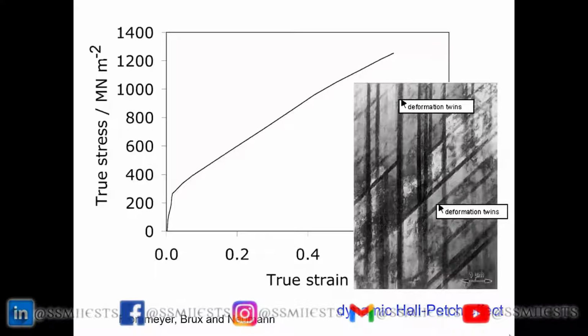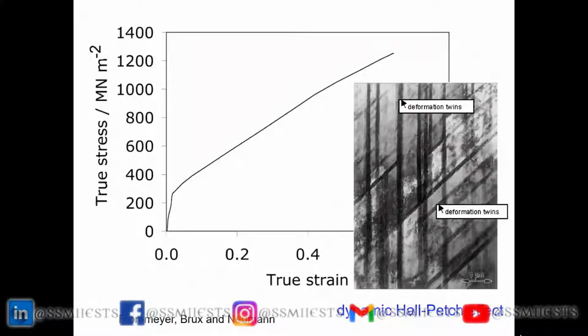Now, I'll go into a few examples. So just when people think that steels have run out of ideas, this particular concept came about. These are the twinning induced plasticity steels, where you start off with quite a small strength of the order of 300 megapascals, and then there is a work hardening mechanism which leads to a strength in excess of 1 gigapascal and an elongation of 60%. That is really quite remarkable. Okay, so an elongation of 60% and a strength of about 1.2 gigapascals. So the mechanism of this work hardening is interesting. The steel contains a very large amount of manganese, and therefore it is a fully austenitic steel.